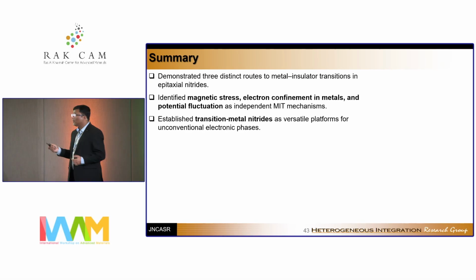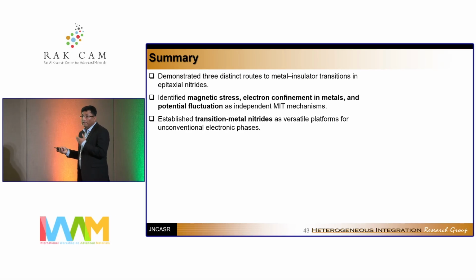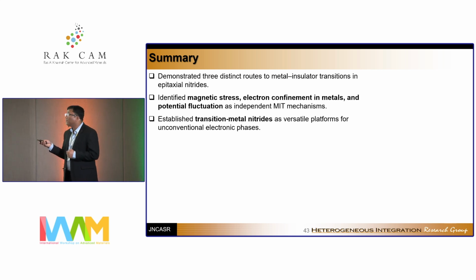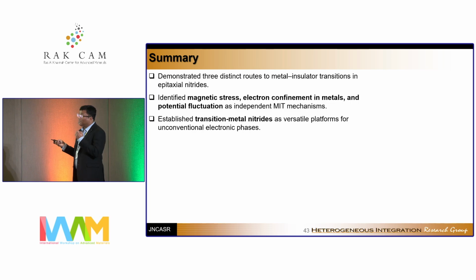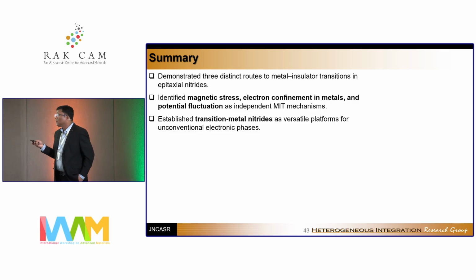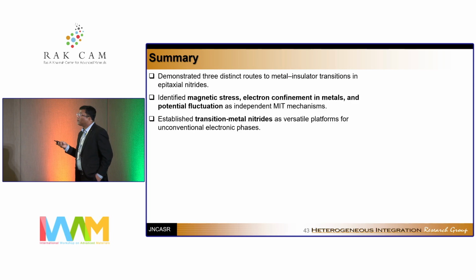In summary, nitrides have been a really interesting and exciting class of materials these days for various applications. One of the things that was missing was a feature of metal-insulator transition, if you want to use it for some devices. Over our work of the last 3 to 4 to 5 years, we have now developed 3 systems where there is a clear metal-insulator transition driven by new physics. In one case, it is magnetic stress, which leads to a metal-insulator transition in chromium nitride, electron confinement in the case of a metal like hafnium nitride, and of course the potential fluctuation in the case of scandium nitride.